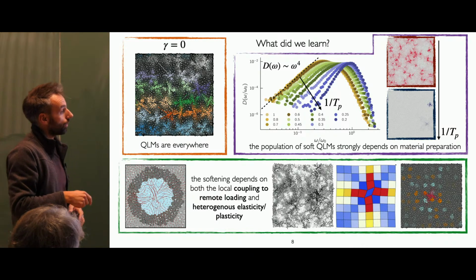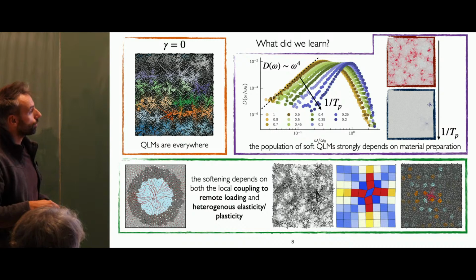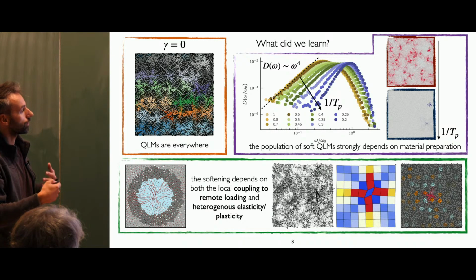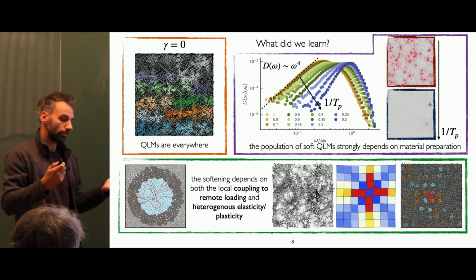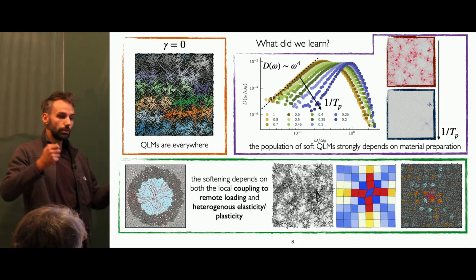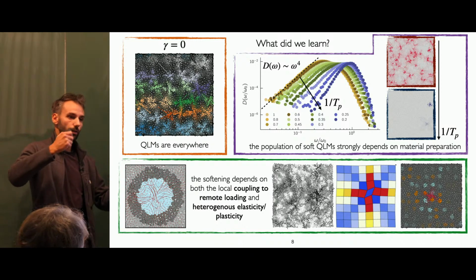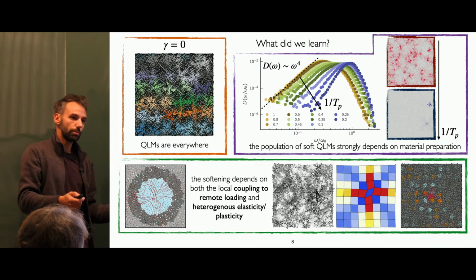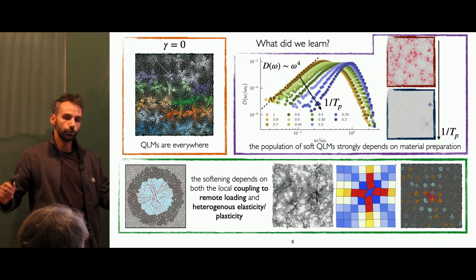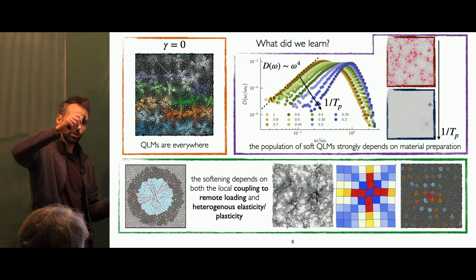And then there will be other coupling, because when you deform your system, you're in a heterogeneous elastic media. So there will be two types of things that can affect the dynamics of a mode. One is just elasticity. If I'm starting to shear my system, I don't see any plasticity. There is no dissipation, no actual rearrangement. I just undergo an elastic branch.